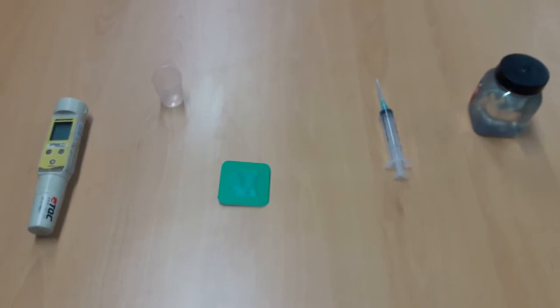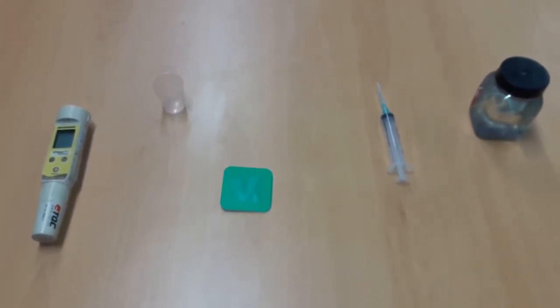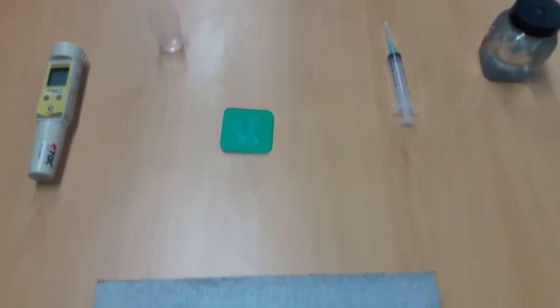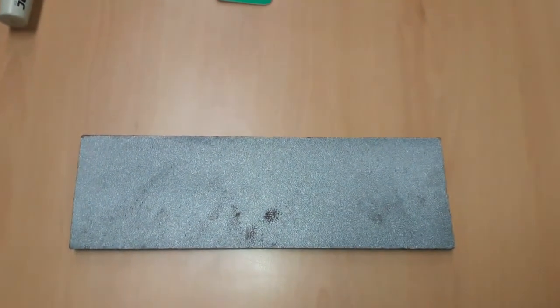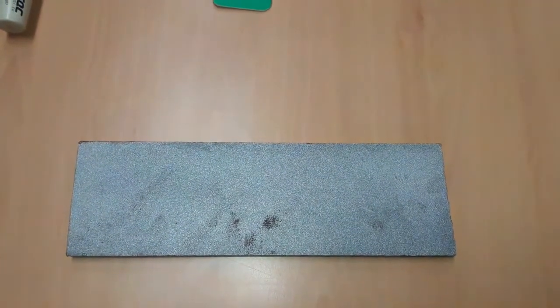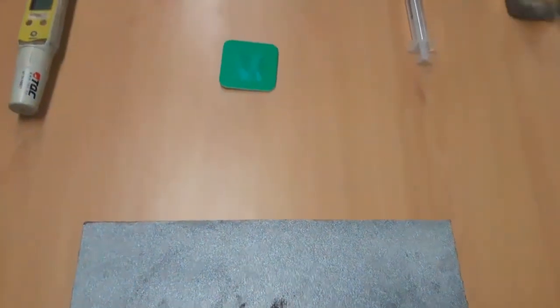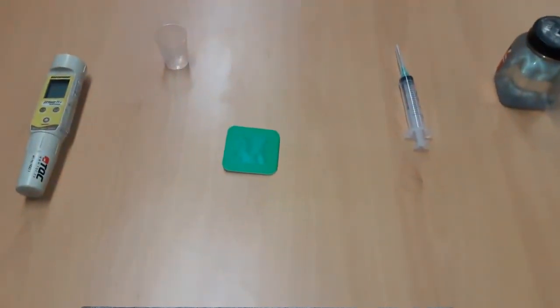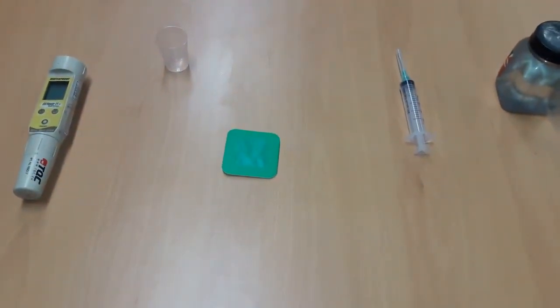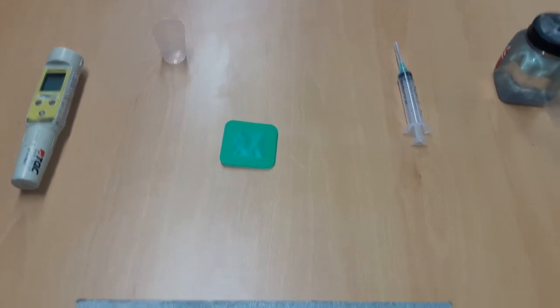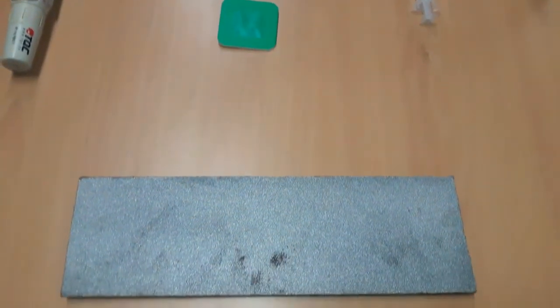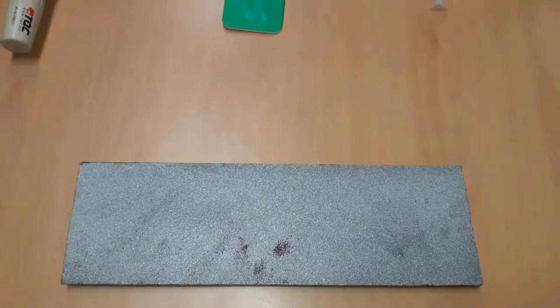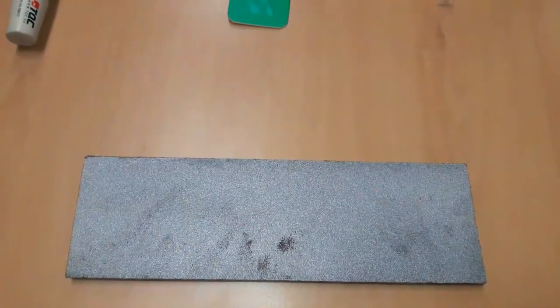Working instruction. Measurements shall be carried out on an agreed section of the block. As per PSPC rule, at least one measurement is required per block. Measurements shall be carried out on the agreed surface after blasting. Also, surface temperature shall be checked and recorded before the measurement. Any cleaning, such as wiping with gloves or a cloth, shall not be carried out before measurement.